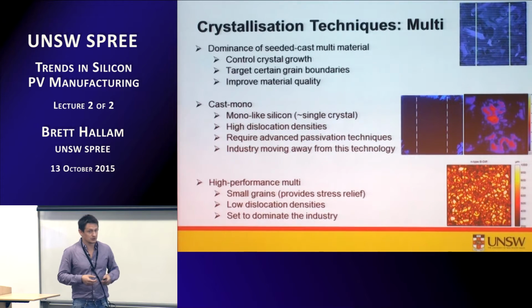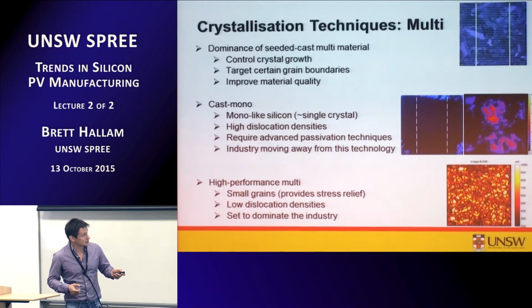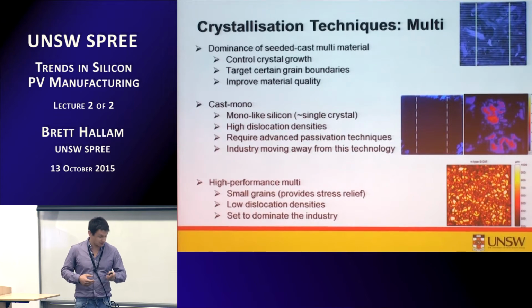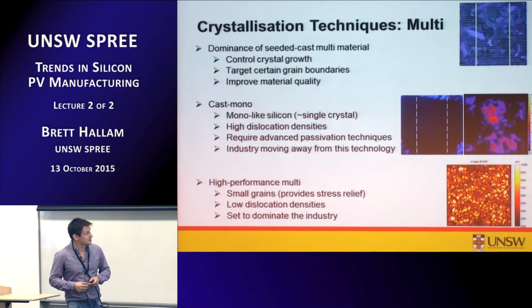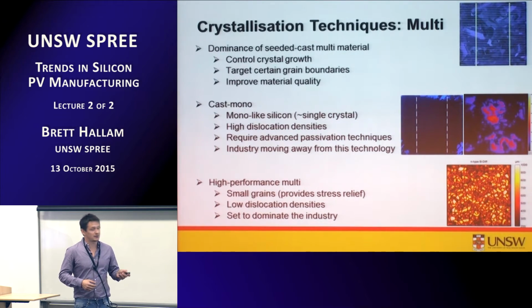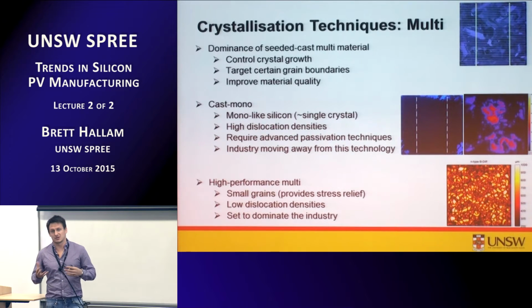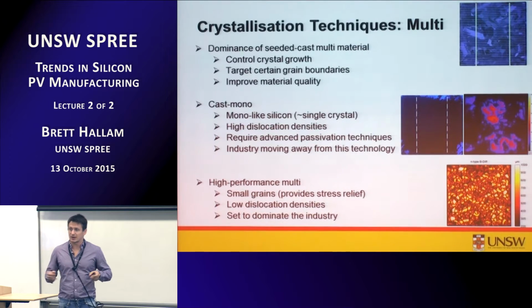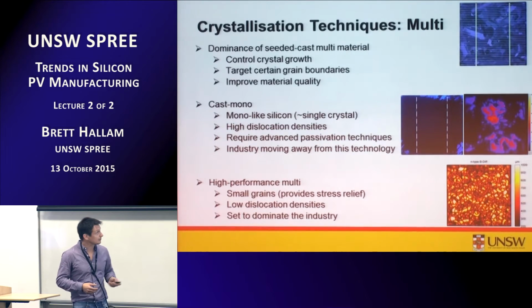So it can lead to more uniform quality of the silicon and higher bulk lifetimes, because within the grain, you get very high lifetimes. It's actually quite impressive, and this is now set to dominate the industry. So the industry has moved completely away from the cast mono technology and is shifting towards this, what they call high performance multi. I think I've covered everything there.